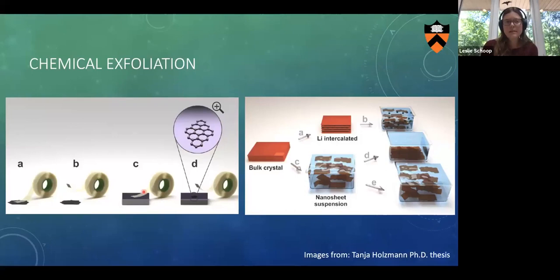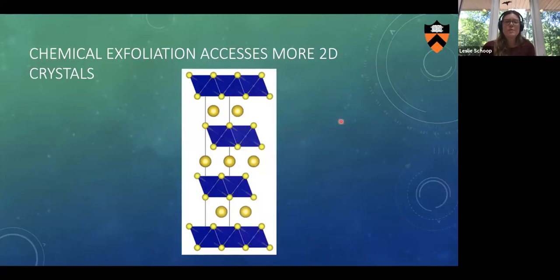This is a completely different field which exists next to that, where you use chemical exfoliation to delaminate materials. You can either start from a bulk crystal, intercalate it first and then delaminate it, or you can start from an intercalated crystal. One of the advantages of chemical exfoliation is that it accesses more 2D materials. So you can exfoliate a material that looks like this. If you stuck a piece of scotch tape to this material, nothing would happen. But with chemistry, you can make a new 2D material. So you just enlarged your material space a lot by this method.